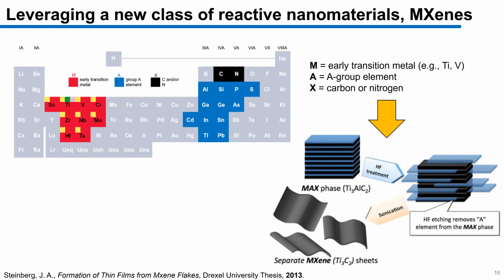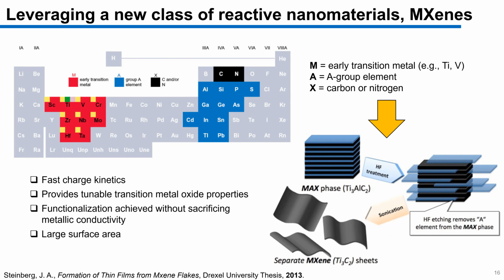There have been a lot of studies on these materials. They're fairly new. They were discovered or formed in 2011, so compared to a lot of existing nanomaterials, they're fairly new. And they've been shown to have very fast charge transfer kinetics. You can tune the properties of this composite by adjusting which transition metal you use. You can functionalize this material further without sacrificing metallic properties that might be beneficial. This is something that you can't necessarily do as well with other nanosheet materials like graphene or graphene oxide. And because of their two-dimensional nanosheet morphology, they have very large surface area. So these are all great properties to have in materials that you hope can promote catalytic processes.